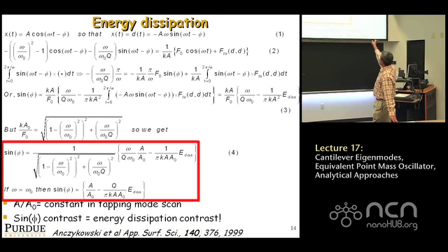So we plug that in, and we get the first of equation 4, which tells you the sine of the phase lag. Phi is the phase lag. All this in terms of energy dissipation per cycle, E-dis. Life simplifies when you choose to do all your experiments at resonance, like hopefully most of you do. So omega is equal to omega 0. Life simplifies to this very simple, very elegant, very important expression: sine of phi equals A over A0 minus Q over pi k A0 times E dissipation. It tells you that the sine of the phase lag is connected to this.